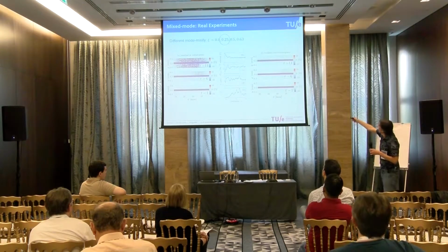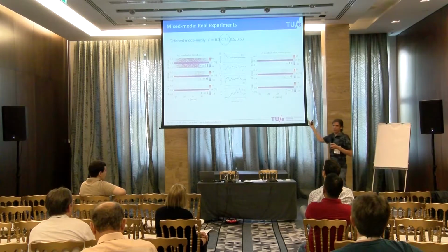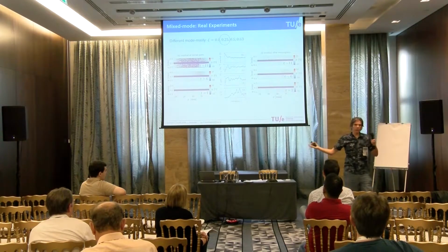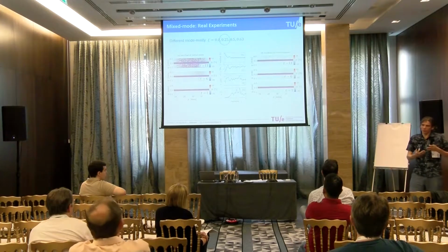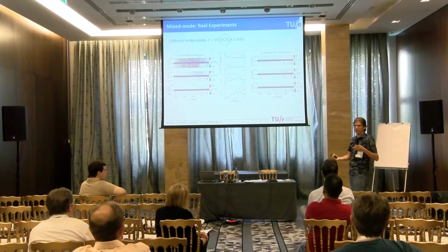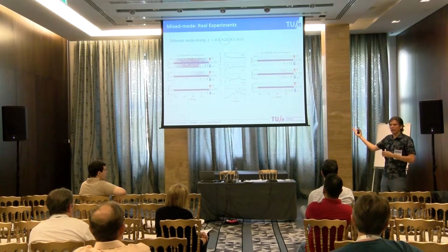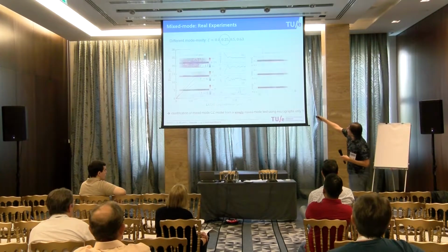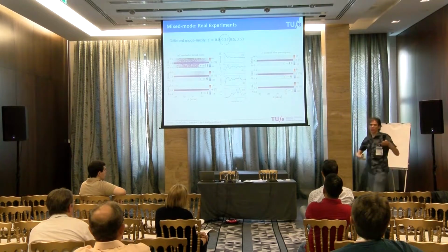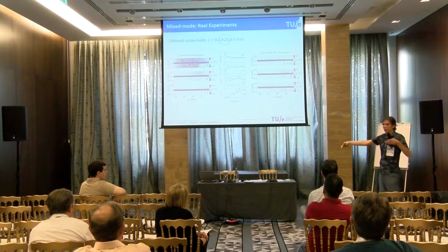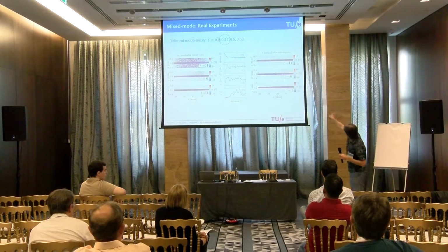these residuals, and then we converge. Now it's not completely zero, and it's probably due to the fact that the model we're using is not perfectly capturing what's happening in the interface. That's also why this test, the 0.5, is basically unstable, while in our numerical predictions that should be correct. But still we're coming close, right?